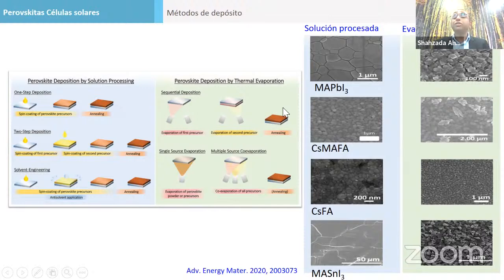Just to give you a comparison of two types of microstructure of the perovskite surface. This one is the solution process. You can see the crystals are relatively larger for MAPbI3. After addition, the perovskite grains became smaller. This is cesium FA, and this is tin-based perovskite. And if you do evaporation of the perovskite, I think the grains are even smaller, much smaller. With much smaller grains, the VOC losses will be higher.